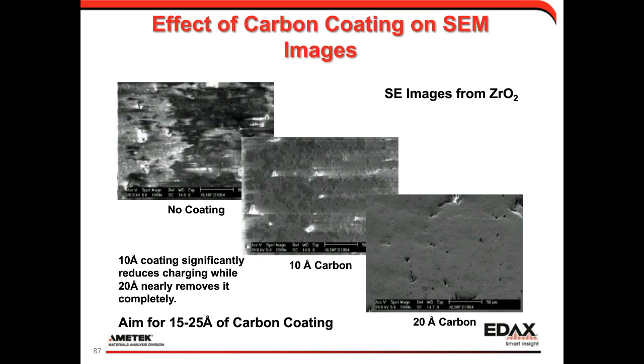And this just shows the effect of coating on your SEM image. So if we get between that 10 to 20 angstroms, we generally get enough that we're removing the charging but still get usable EBSD data.